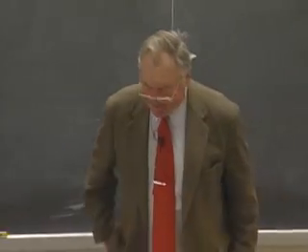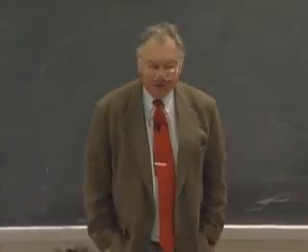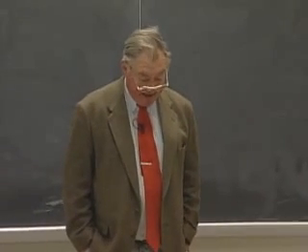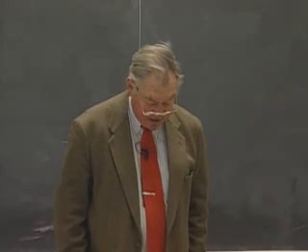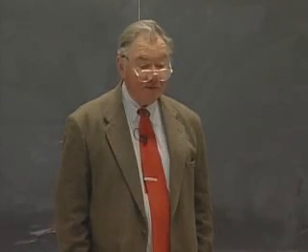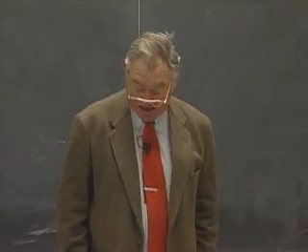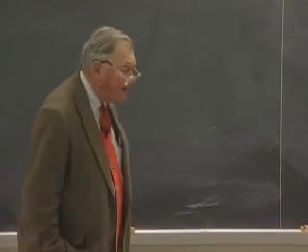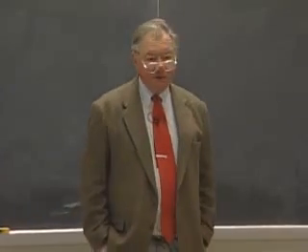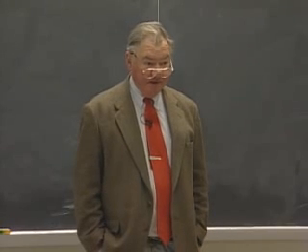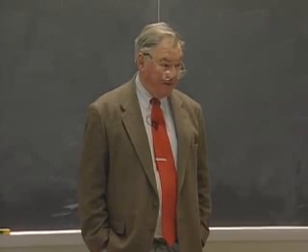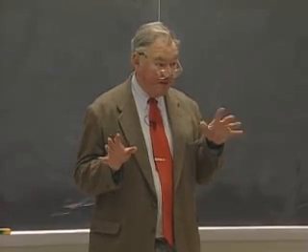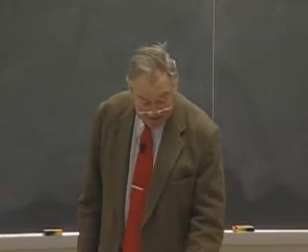What I'm going to do today is to talk a little bit more about fourth rank tensor properties, which we've not said much about. I'm going to look at some scalar moduli and look at them for a couple of different symmetries and restrictions on the compliances. The surfaces, as you might expect, turn out to be really, really weird because these will be fourth order variation with the direction cosines. So when you take trigonometric functions and raise them to the fourth power, you get severe anisotropies for a great many of these scalar moduli.